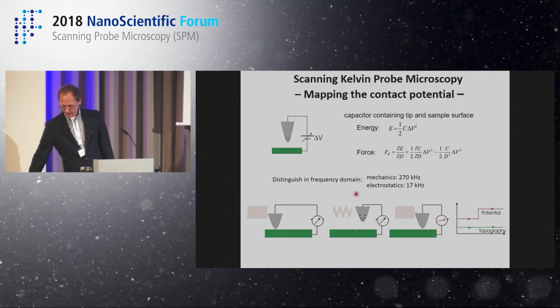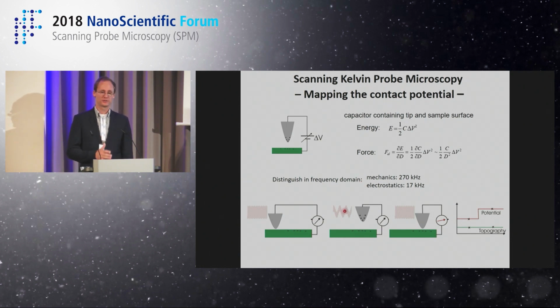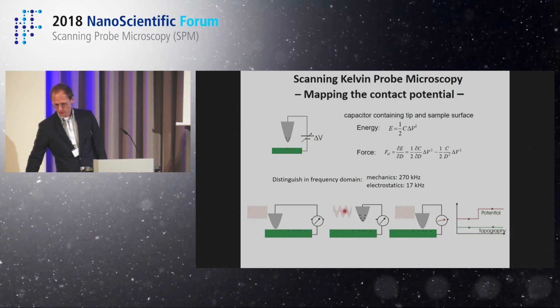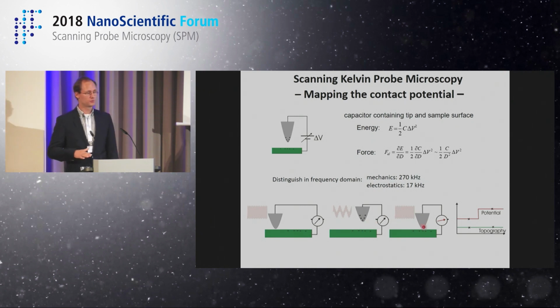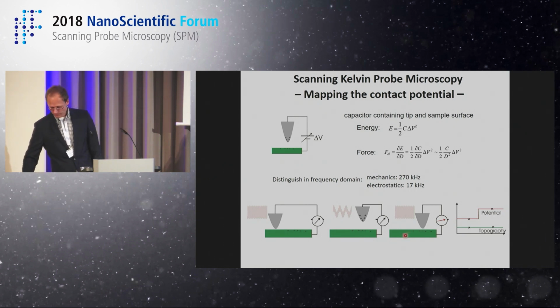And now, by applying an AC voltage at 17 kilohertz, for example, what happens is if there are electrostatic forces, we see that our tip, in addition to the high-frequency oscillations of non-contact mode, has an additional oscillation at 17 kilohertz. And if we just track this oscillation and apply a DC voltage in order to remove it, then we exactly know that we are at the condition where there are no further charges present at our tip. So we again would approach the surface. There is no electrostatic interaction, and we wouldn't see the artifact in surface height. So the topography would be correct.